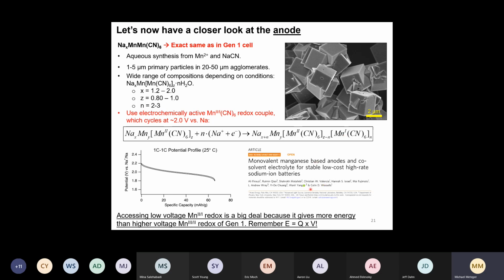So this was a pretty big deal because this low voltage redox activity of these low cost Prussian blue analog materials was not really well documented in literature. They published this article on that, monovalent manganese-based anodes and co-solvent electrolyte for stable, low cost, high rate sodium-ion batteries. So the reason why this is nice is this low voltage manganese redox gives you more energy than the high voltage manganese 2+, 3+ redox of the generation 1 cell, because the energy of the cell ultimately is, of course, the capacity times the average voltage.